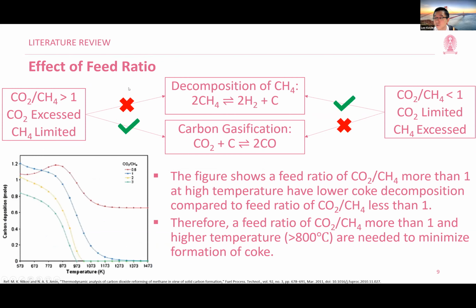Next is the feed ratio. Feed ratio meaning the feed ratio of carbon dioxide to methane, so more than 1 and less than 1. As you can see in the figure here, if it's more than 1, so meaning 1, 2, 3, the coke deposition decreases as the temperature increases. However, if the feed ratio is less than 1, the coke deposition actually remains constant even at high temperature.